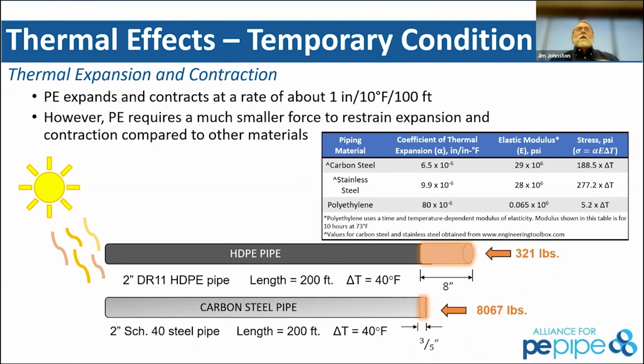Okay, sorry. So a 2-inch Schedule 40 pipe in its contraction will actually have almost 8,000 pounds of force in its contraction. However, that longer expansion in a 2-inch HDPE pipe will be 321 pounds, because the elastic modulus is so much smaller than those other materials. So your restraint requirements on those larger pieces is so much greater.